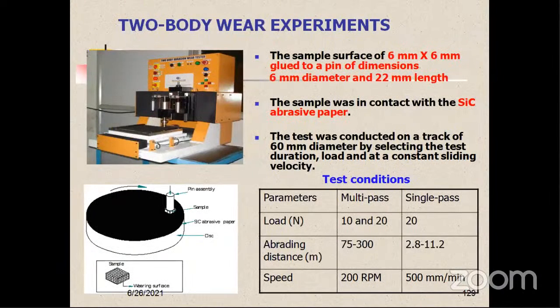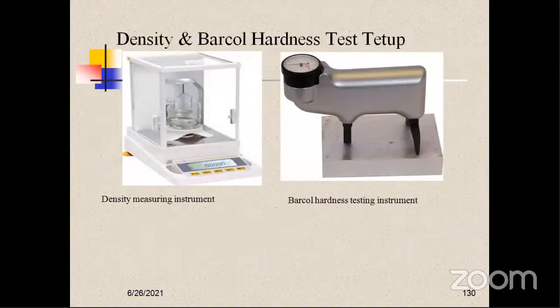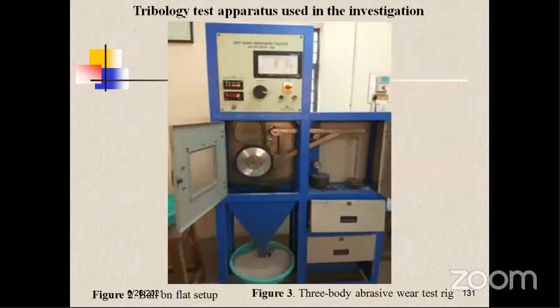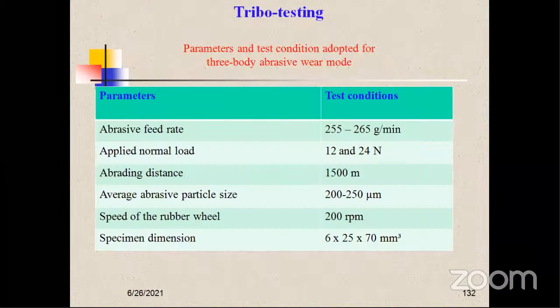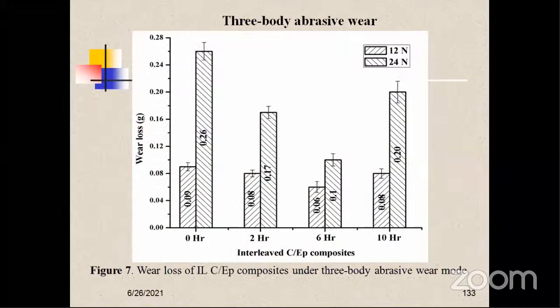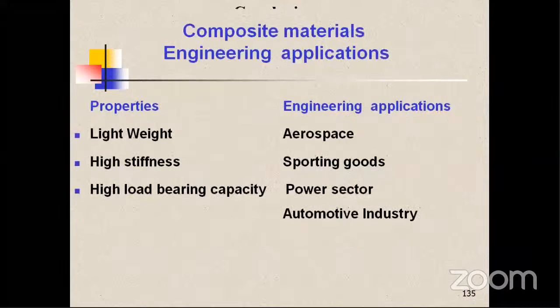So this is the single pass condition wear test we studied for these materials. And as I said, these facilities are available to know the density and also for exact weight loss measurement. We have a 0.1 milligram accuracy weighing machine with density measuring kit. And for hardness, for majority thermoset or thermoplastic polymer composites, you can think of either Barcol hardness or Shore hardness. So this is the three-body abrasive wear tester as per ASTM G65 standard, and various parameters are accounted here, and these are the results and finally conclusions.